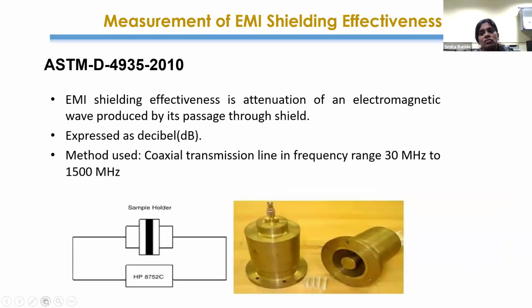Then, as I said, based on the conductivity, we can use it for various applications. So in BTRA, we can measure the shielding performance of the conductive textile using the standard test method, that is the coaxial transmission line method as per ASTM D4935. Here, shielding performance is generally measured in terms of shielding effectiveness in decibel.